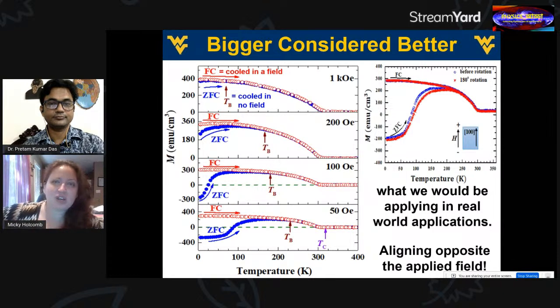Now, this is what I basically told my student for months, that he was doing something wrong. I was convinced that it was some sort of artifact in our measuring system. I'll show some more verifications soon. Another thing was, this deviation between zero field cooled and field cooled is known to come from anisotropy in systems. So one of the logical things to think of was, maybe we just have some preferred magnetic direction, which for whatever reason is exactly opposite to the direction that we're applying our field. And if we apply a large enough field, it counters it. So maybe that's what's going on.